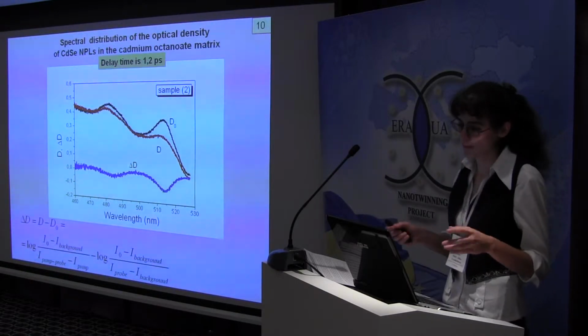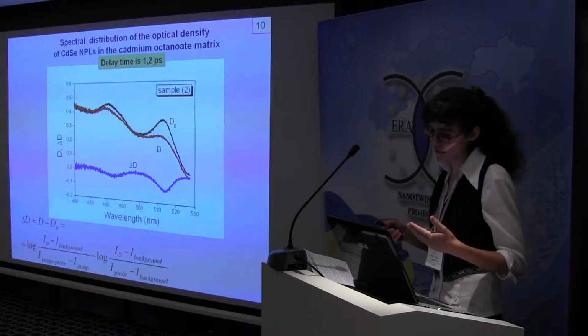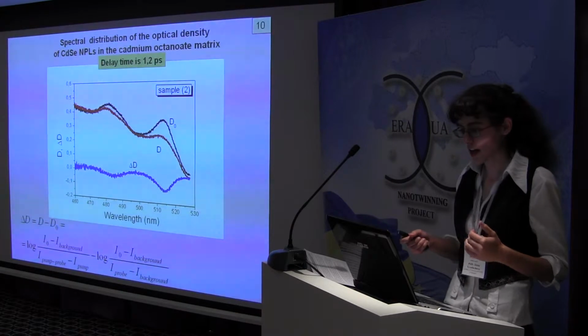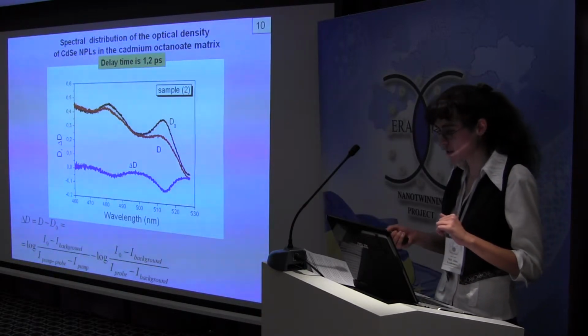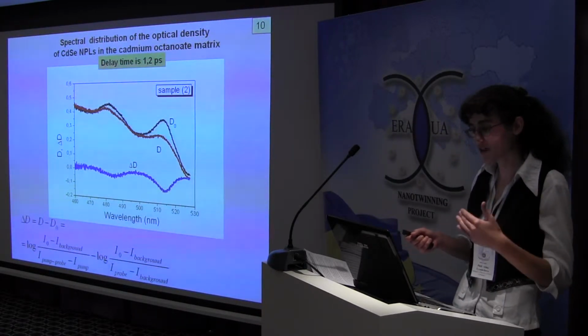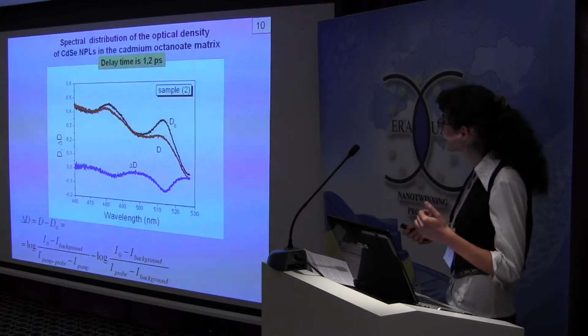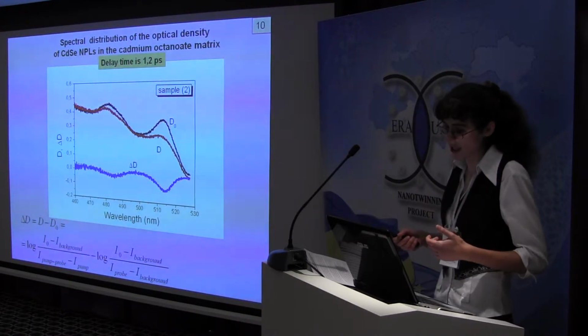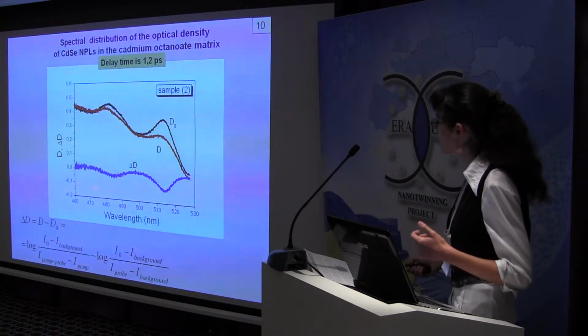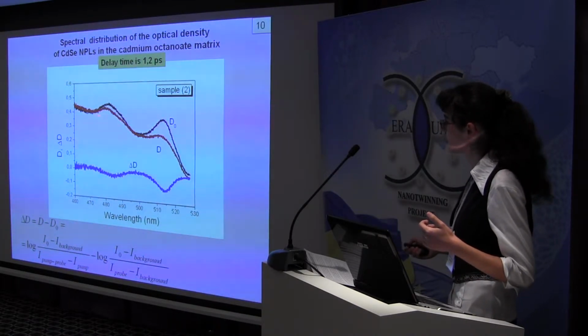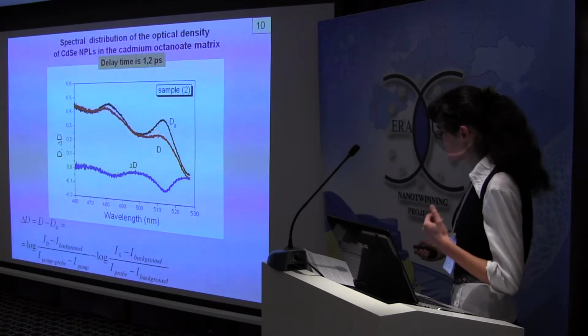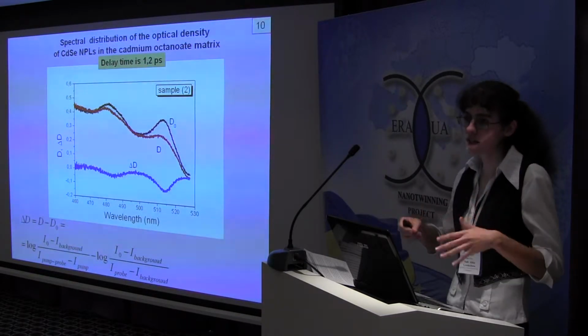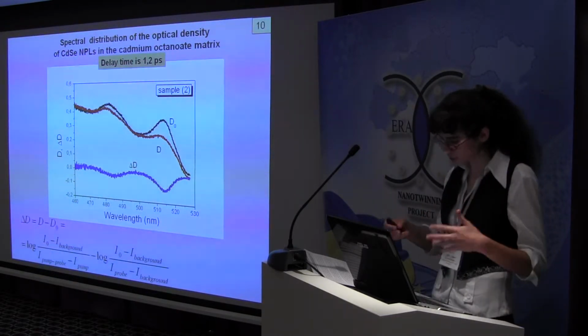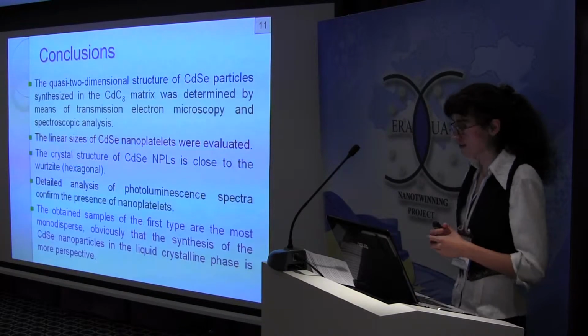We also investigate the optical density variation under strong pulse irradiation. And we observe a decrease of optical density under the pulse, so transient induced transparency is observed.